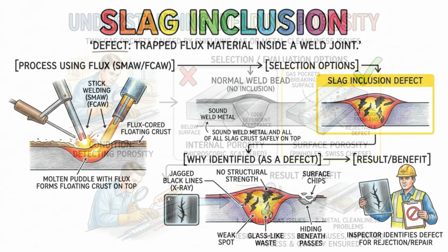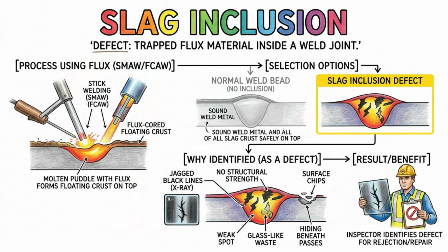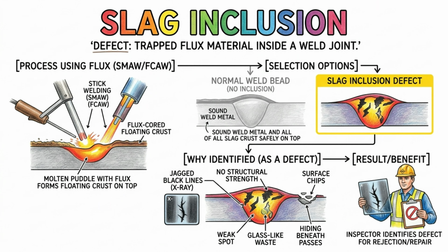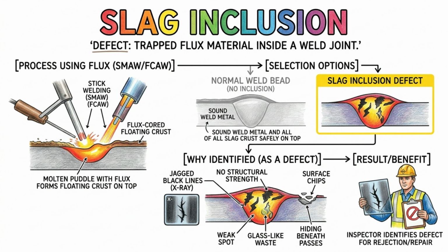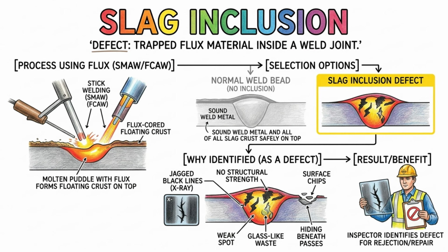Slag inclusion is a defect unique to welding processes that use flux, such as stick welding or flux cord welding. This happens when chunks of solid flux become trapped inside the molten weld metal instead of floating safely to the top as a crust. Because slag is essentially glass-like waste material, it has zero structural strength and creates a massive weak spot inside the joint. As an inspector, you must watch for jagged black lines on X-ray films or surface chips that reveal trapped slag hiding beneath the final passes.